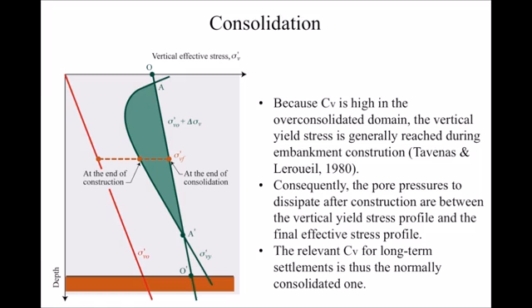Consolidation. In fact, because CV is high in the over-consolidated domain, the vertical yield stress is generally reached during construction. That means that at the end of construction, generally, the vertical effective stress is on the pre-consolidation pressure profile, which means that in the long term, the pore pressure to dissipate is the one shown in green here, in the normally consolidated range, which means that the relevant coefficient of consolidation is the one in the normally consolidated range.